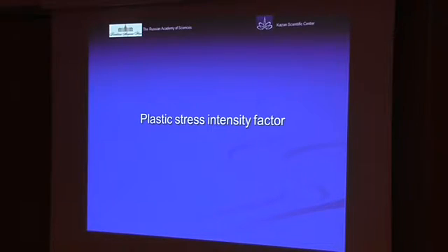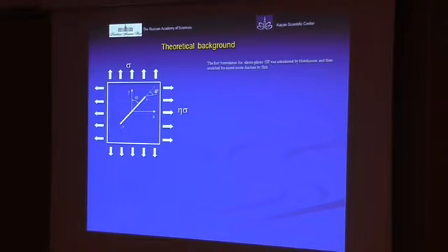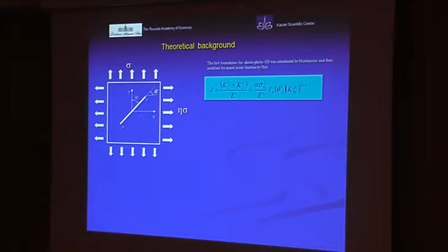First, the nonlinear stress intensity factor is the plastic stress intensity factor. The theoretical background of the plastic stress intensity factor is the well-known Hutchinson-Rosengren-Rice solution. In this figure you can see the well-known solution of Hutchinson-Rosengren-Rice, and the next equation describes the plastic stress intensity factor.